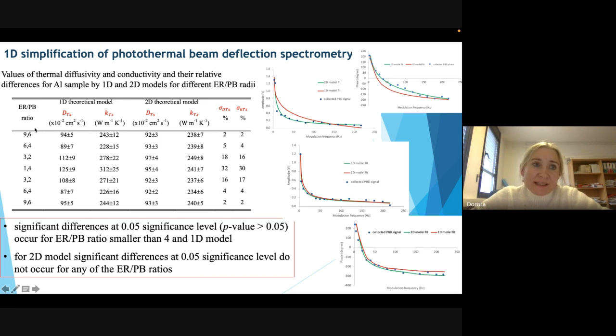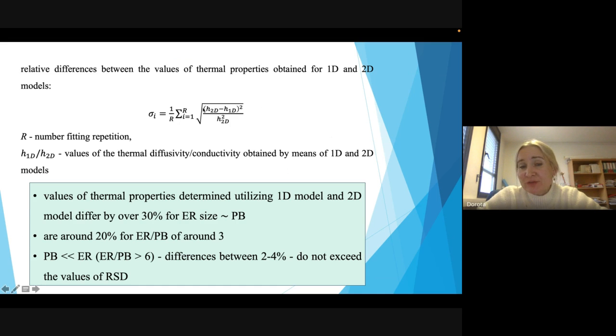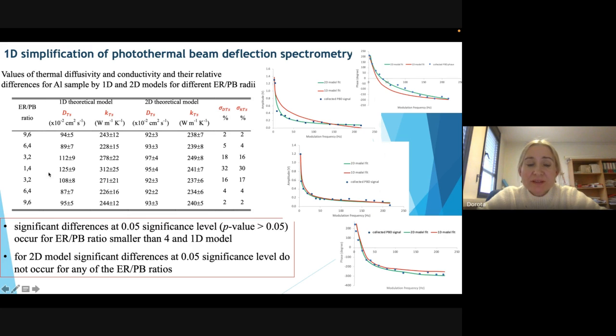And what we can see, if we now compare the results for the 1D model between themselves, we see that significant differences at the 0.05 significance level occur if the probe beam ratio is smaller than 4. So we obtained very, very different results. Such differences do not occur in the case of the 2D model. What is more, if we now compare the results obtained for the 2D model and the 1D model, we can say that if the probe beam radius is comparable to the excitation beam radius, the differences between obtained properties reach about 30%.